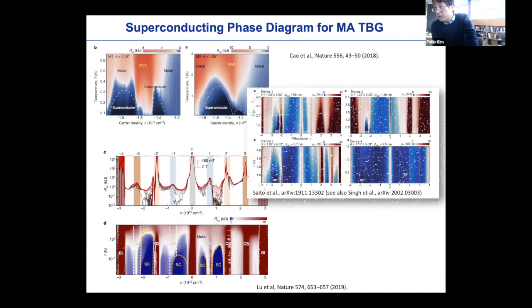Even more so, the most recent report was done by Andrea Young's group, and I believe the Caltech group showed similar things. They also demonstrate that at different angles, slightly away from the magic angle, they also see superconductivity at low temperature. But in this particular case, it is not necessarily right next to or nearby the correlated insulating regime. So there is some speculation, experimentally at least at this angle of the sample, that the superconductivity might be a separate issue from the correlated insulator that people have seen.